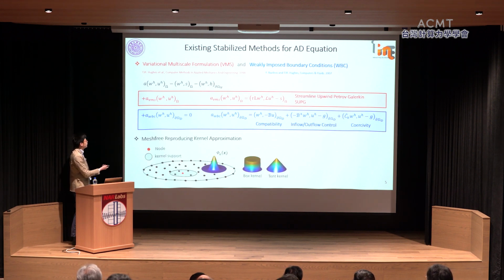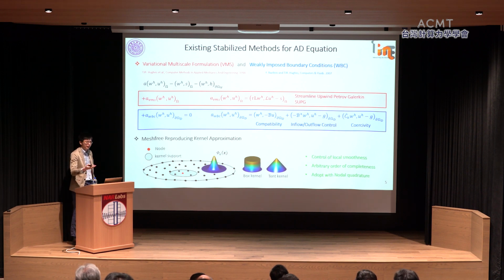And here we choose Meshfree reproducing kernel approximation due to the advantage that Chen had mentioned before, the control of local smoothness, the order of completeness, etc. And because of each Meshfree method, we usually adopt nodal quadrature. But the methodology that I show next does not restrict to Meshfree. You can do that for IGA, for FEM as well, as long as you are using low order quadrature.